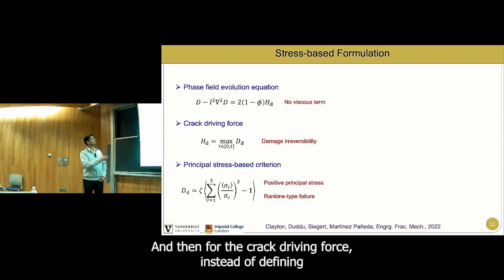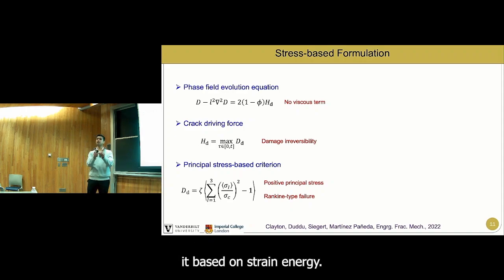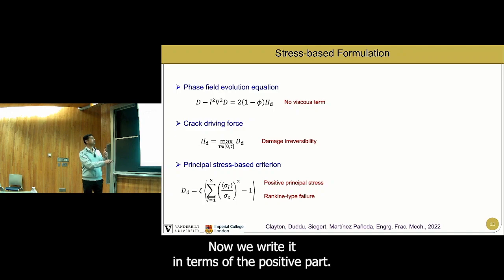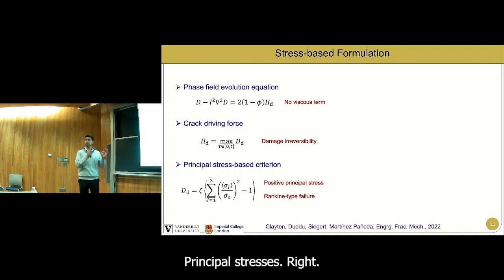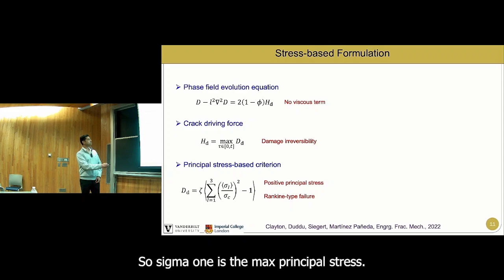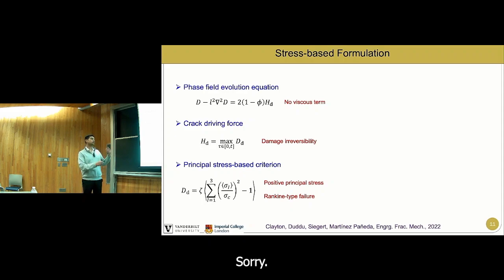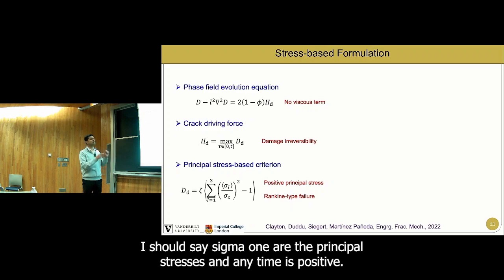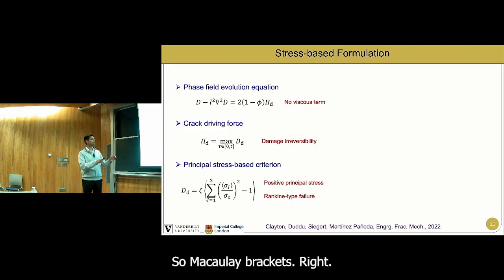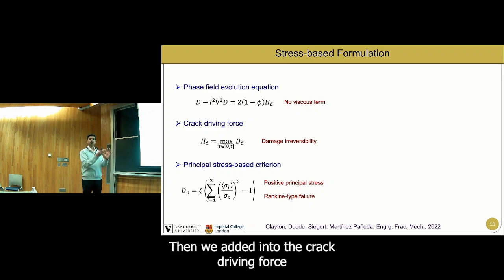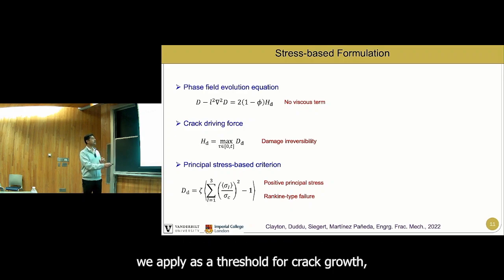And then for the crack driving force, instead of defining it based on strain energy, now we write it in terms of the positive principal stresses, right? So sigma 1 is the max principal stress. I should say sigma 1 are the principal stresses, and anytime it's positive, so Macaulay brackets, right? Then we add it into the crack driving force. We apply a threshold for crack growth, and then you get this formulation.